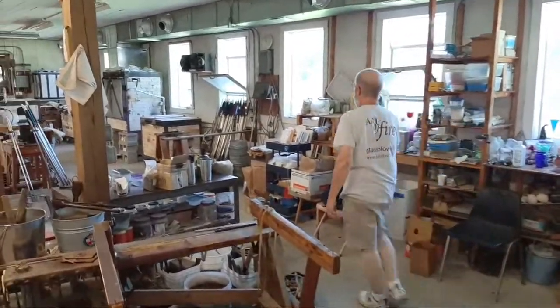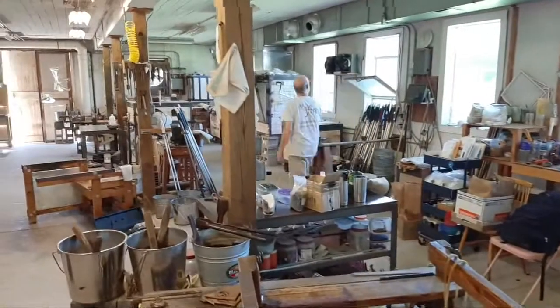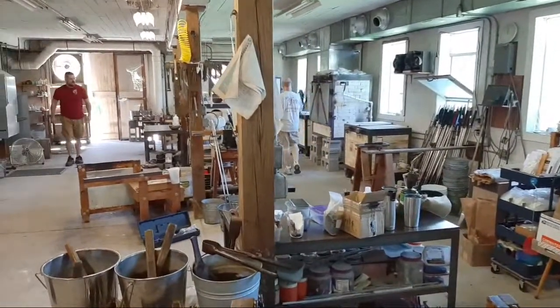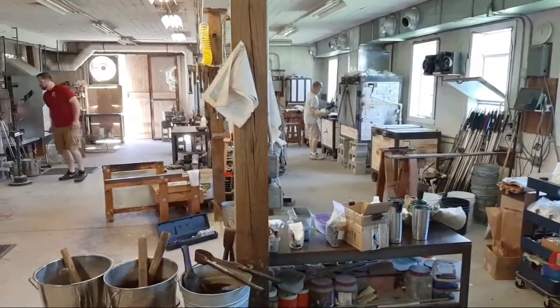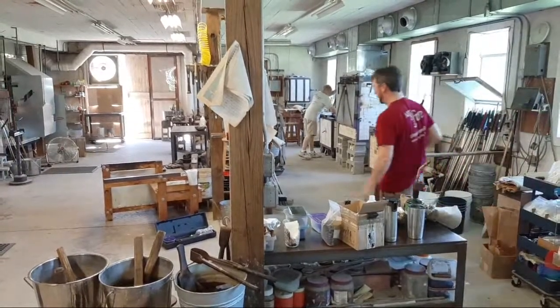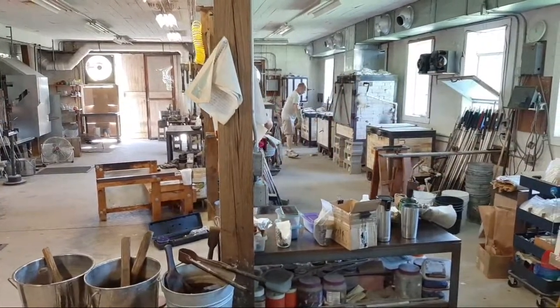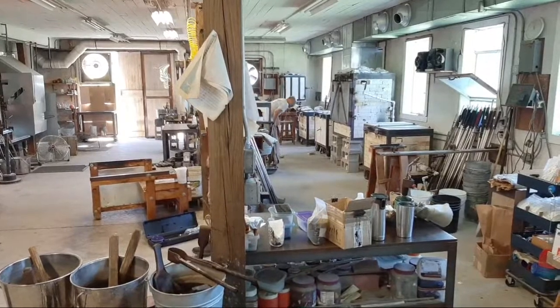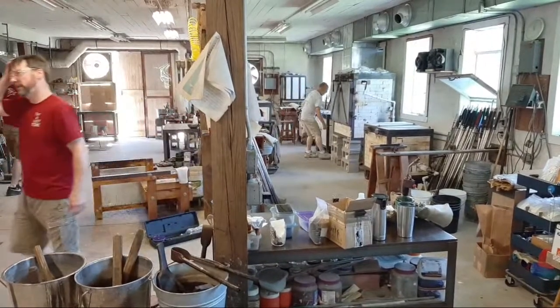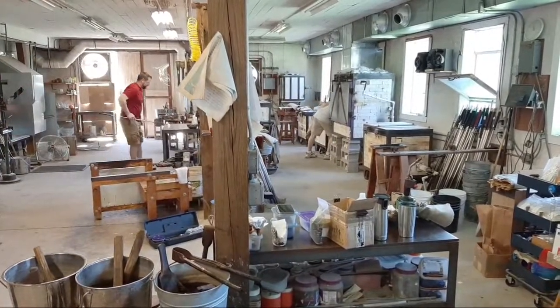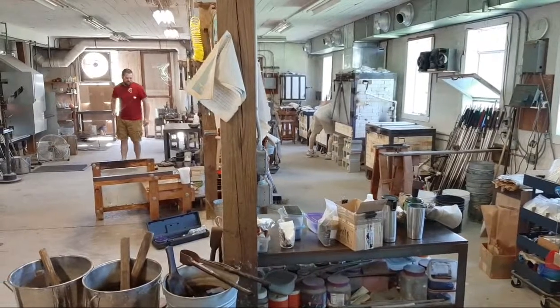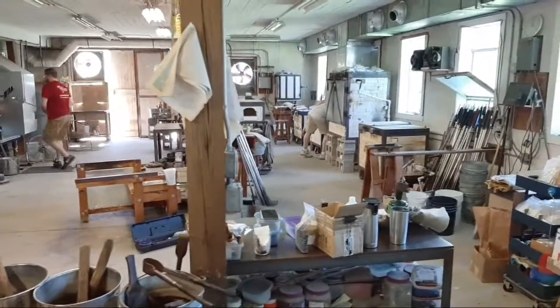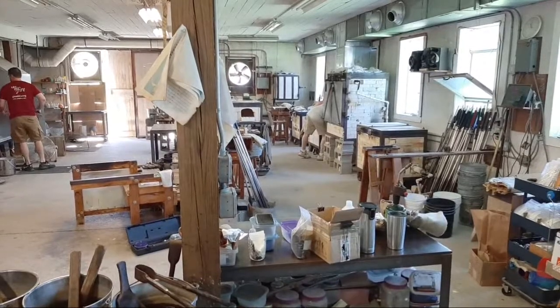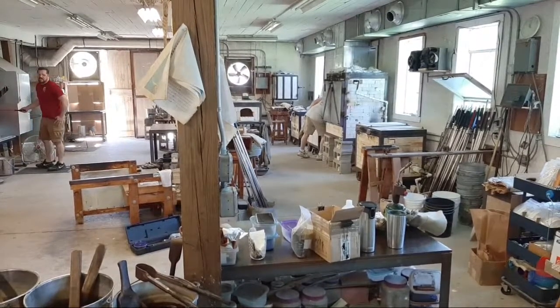There's our finished piece. And now for the longest part of the glass blowing process, the annealing. It's going into a box of bricks that's held at 900 degrees all day. The glass can go to that temperature with no ill effect, but if it were to crash from 900 degrees to room temperature too quickly, it would shatter. So when we turn that off at the end of the day, that's how we control the heat loss overnight, and the piece will come out tomorrow morning.